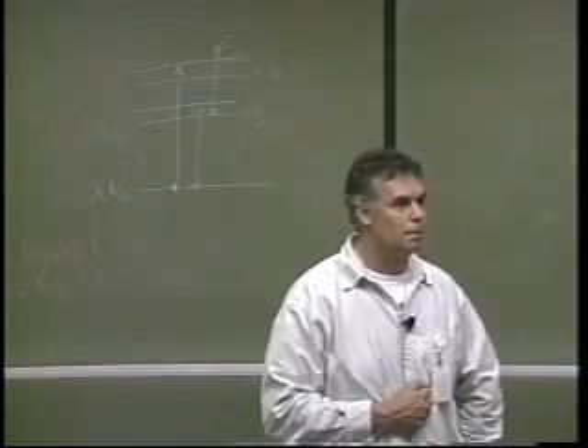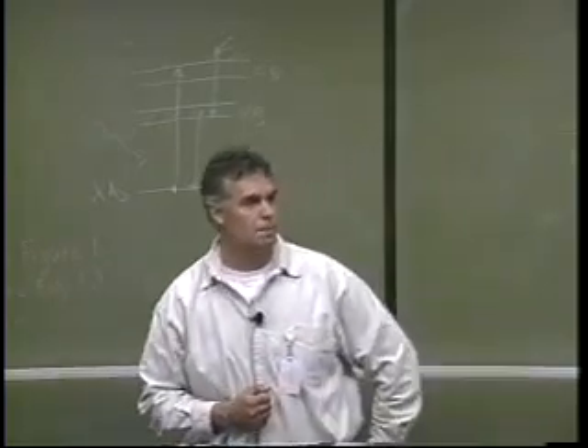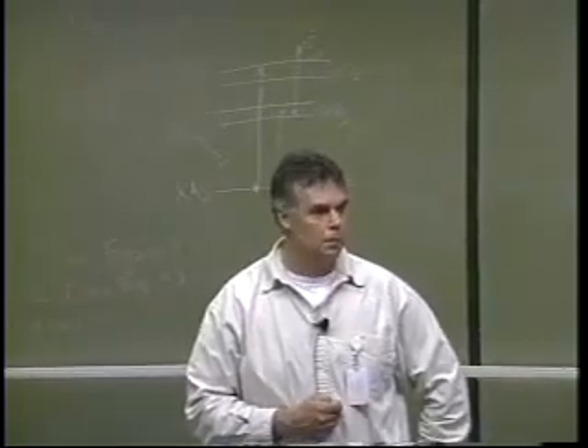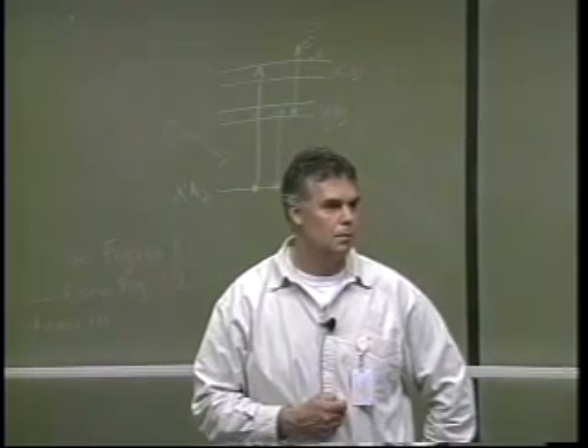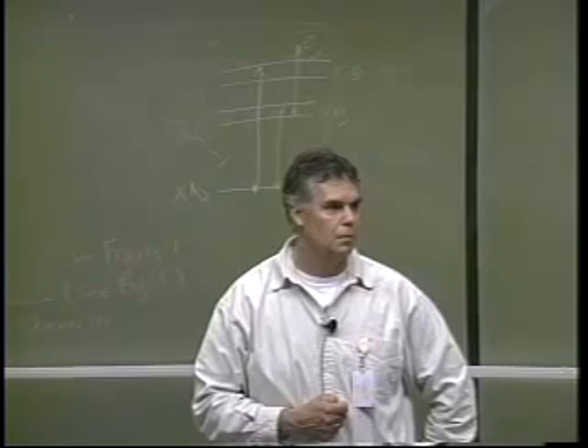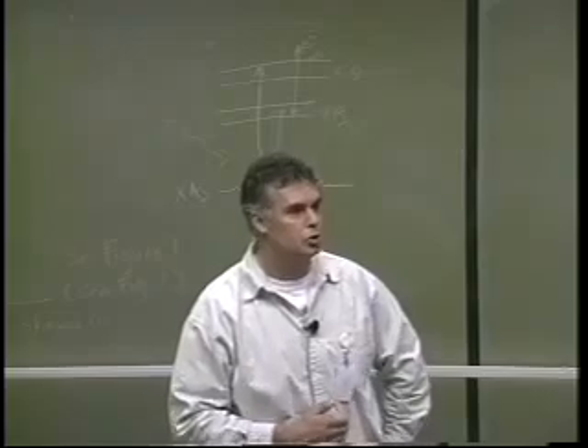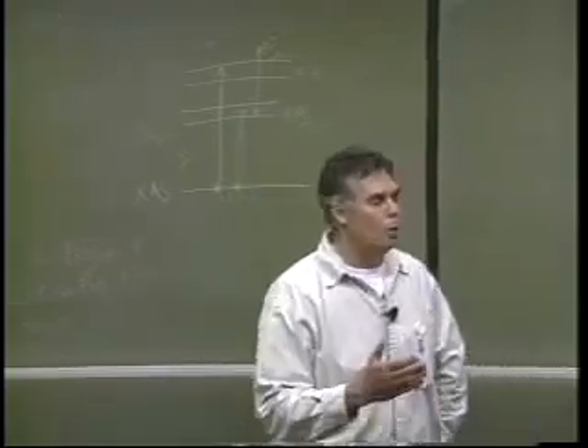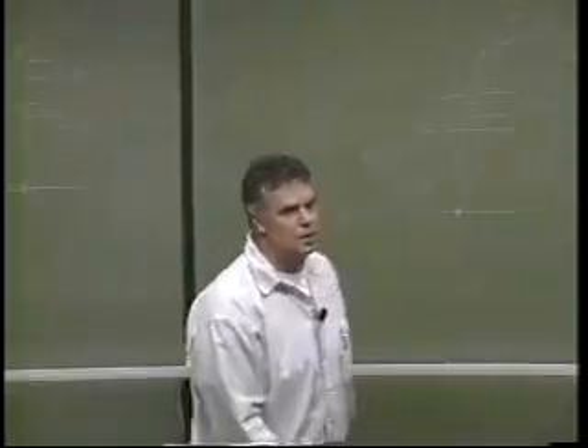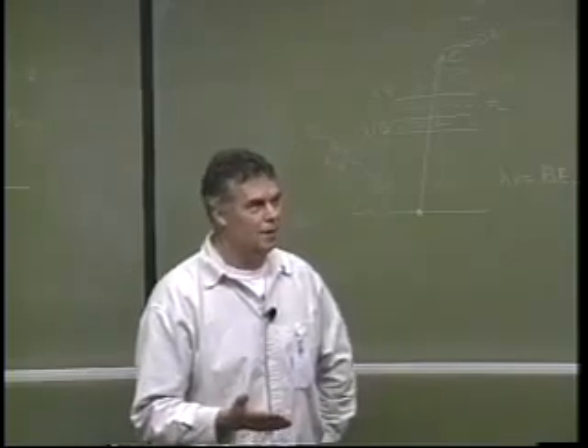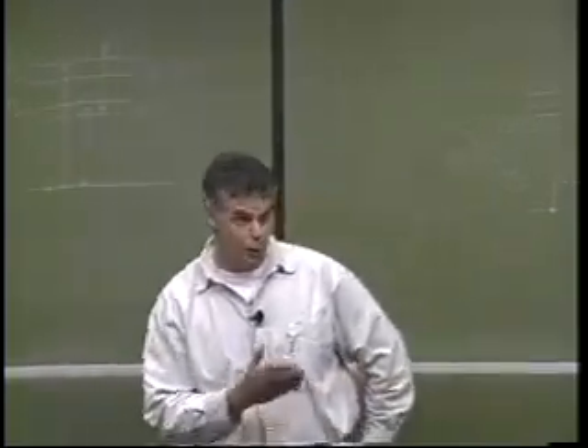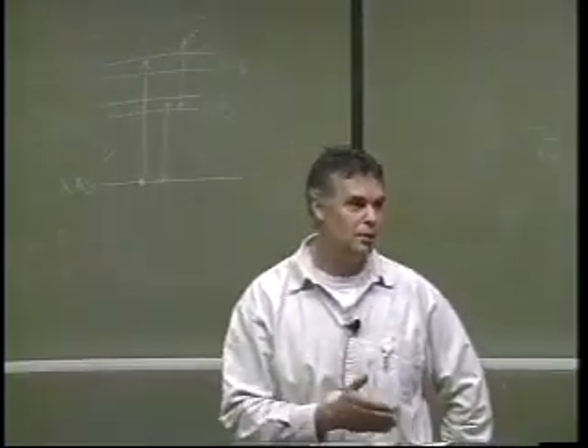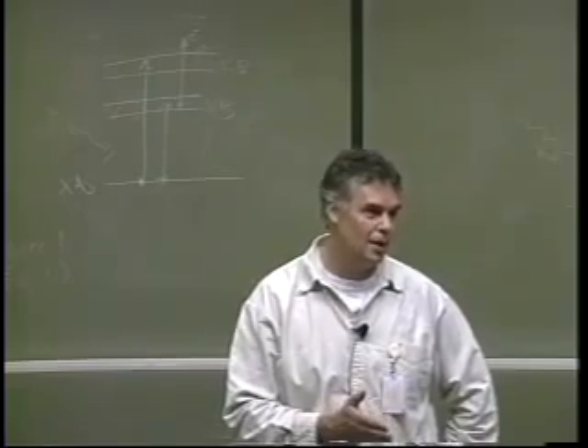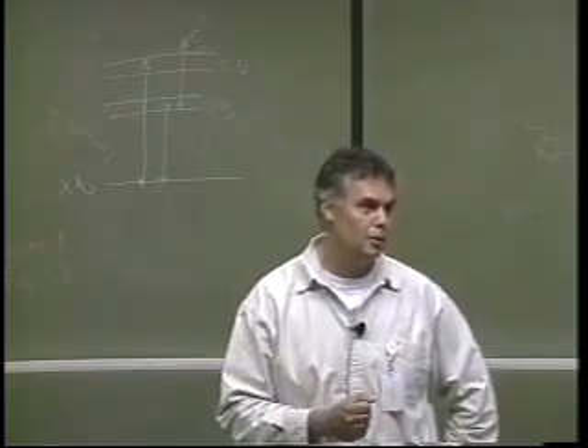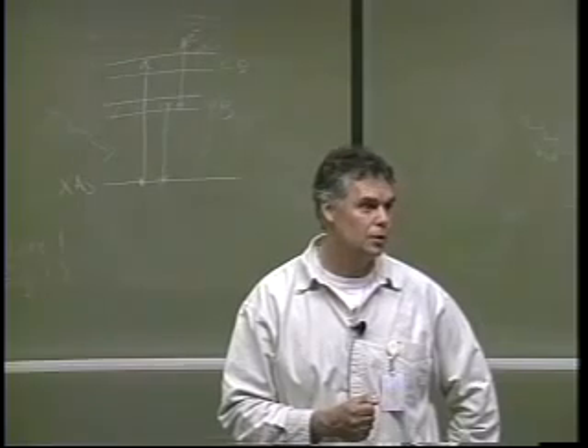I see. Okay, so that helps, actually. So there's an electron dropping down in some radial direction, and by this simple model, there's a radial ejection of some other electron. Sure. I see. Now, it's more than we were thinking, at least for myself. That doesn't explain, per se, why your original question is why lighter Z, the Auger process, dominates, whereas for higher Z, especially for K and L, you get